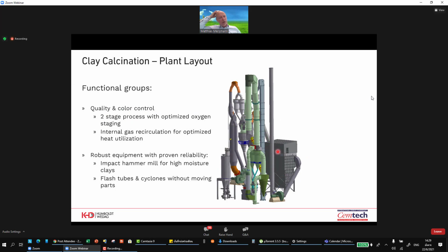As a special feature, we have developed a specific two-stage process with optimized oxygen staging, which provides for color control and optimized heat utilization. This is necessary because if you don't control the oxygen content during the calcination, you will have a non-gray product, and in the cement industry we just like the color of gray. And with this it's possible to control the oxygen content and with that to control the color.